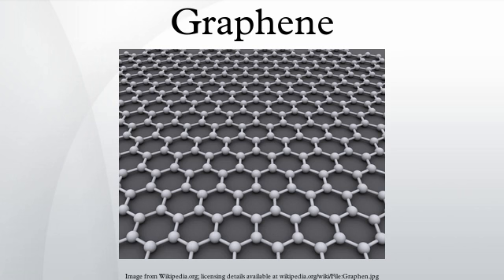Saturable absorption. Such unique absorption could become saturated when the input optical intensity is above a threshold value. This nonlinear optical behavior is termed saturable absorption and the threshold value is called the saturation fluence. Graphene can be saturated readily under strong excitation over the visible to near-infrared region, due to the universal optical absorption and zero band gap. This has relevance for the mode locking of fiber lasers, where full-band mode locking has been achieved by a graphene-based saturable absorber. Due to this special property, graphene has wide application in ultrafast photonics.